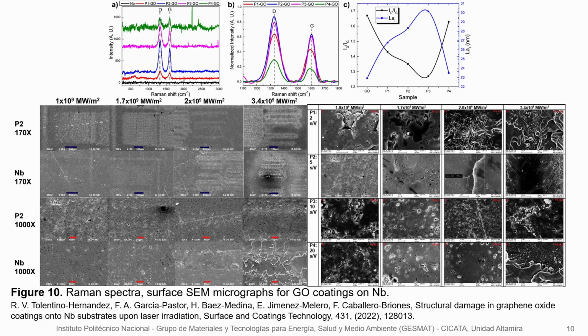From the Raman analysis, they discovered that there is some kind of reduction of the graphene oxide to a partially reduced graphene oxide. They found an optimal deposition time with the best thermal resistance to the laser, a deposition time of 10 seconds, and show that this sample protects even at an energy fluence of the laser of 3.4 x 10^9 megawatts per square meter.